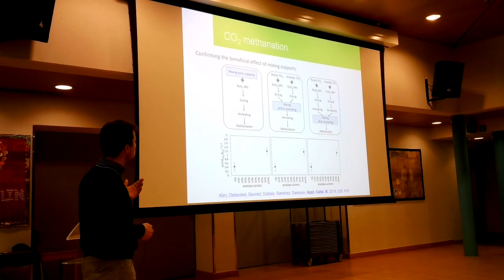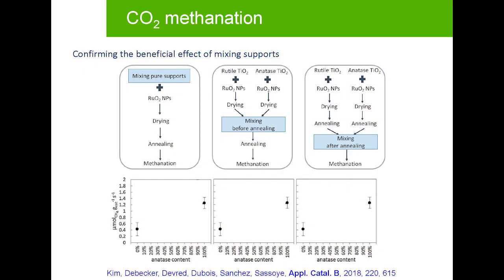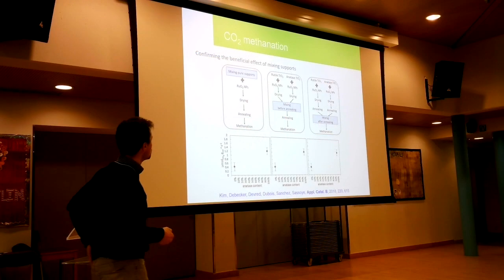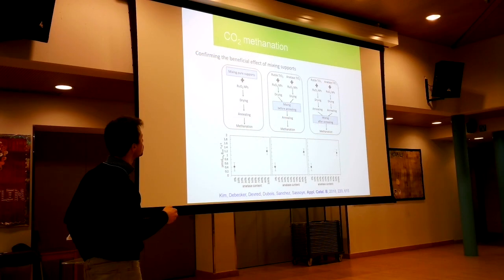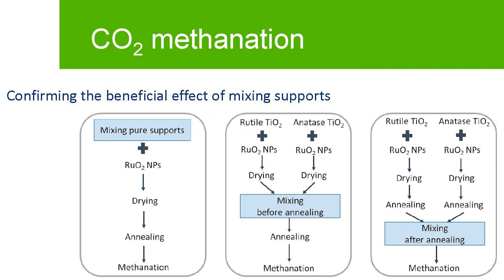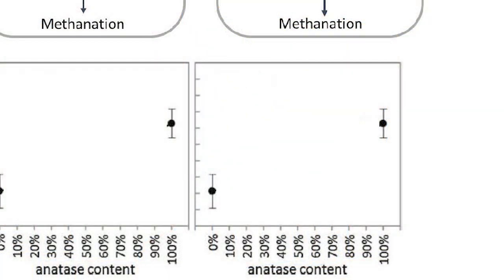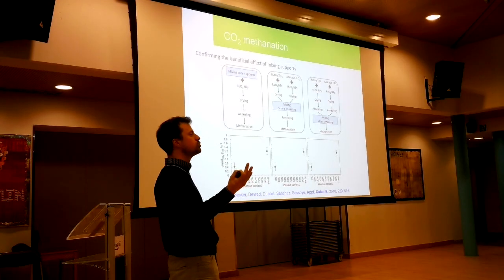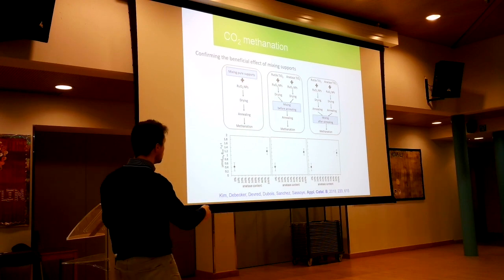And of course, knowing this, we wanted to check, to prove it experimentally. So we did an experiment where we took our two catalysts, the rutile TiO2 plus ruthenia after drying and calcination, and then the other one with anatase, and in the end we mixed them together. So this is the performance of the rutile one, this is the performance of the anatase one. If we mix them together, for example 50-50, where should we land in terms of activity? Just in between, on the line, right? So that's what we did, and that's what we found.